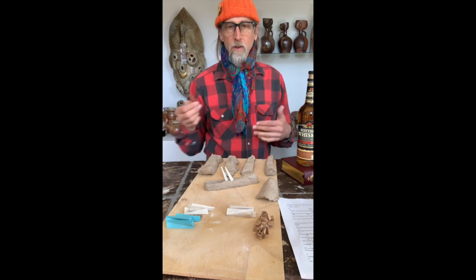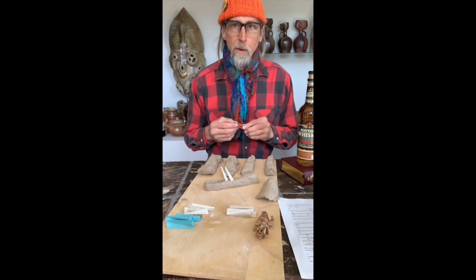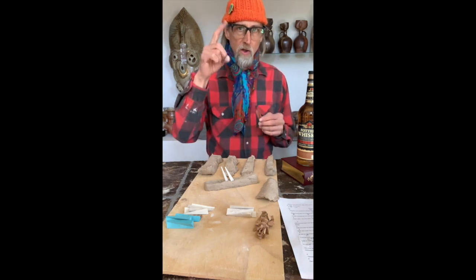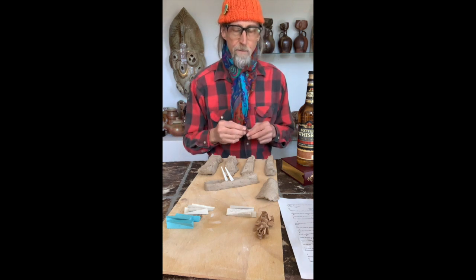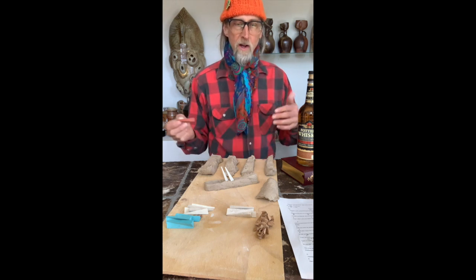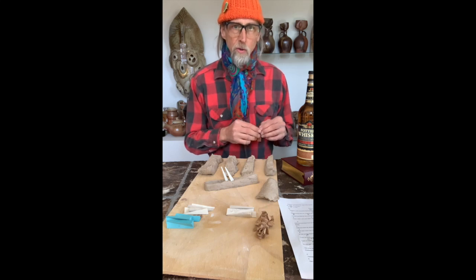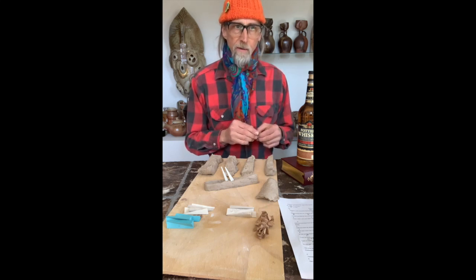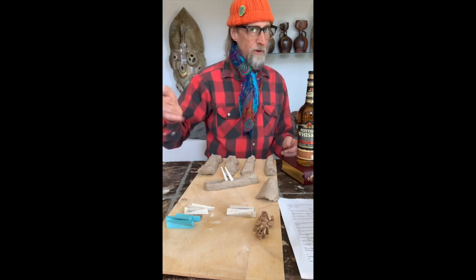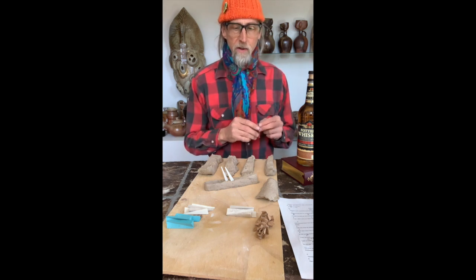Now, in a wood kiln, quite often you're cycling between reduction and oxidation, so it may be a moot point for some people. But I like to know when that is, and I give it a little hard reduction when 010 is going down, because that's when my Shinos start fluxing out. I don't want a heavy one, because I could still carbon core then, and carbon coring is one of those things. So you don't ever want to think about too much fuel going in at the beginning of your firing. You can over-stoke a kiln after your body cones go down, and generally be okay, but you want to think about these issues, okay?